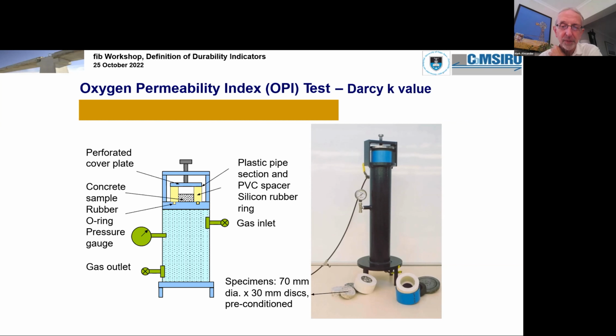The specimen is obviously preconditioned in a certain way, and the specimens are roughly 70 millimeters diameter, 30 millimeters thick. And the reason for that 30 millimeters is roughly to characterize the cover layer. Remember, it's the cover layer that is of concern to us here, not the bulk of the concrete. So this cover layer is very sensitive to all kinds of things, and we have to characterize that particularly rather thin section of the overall structure.